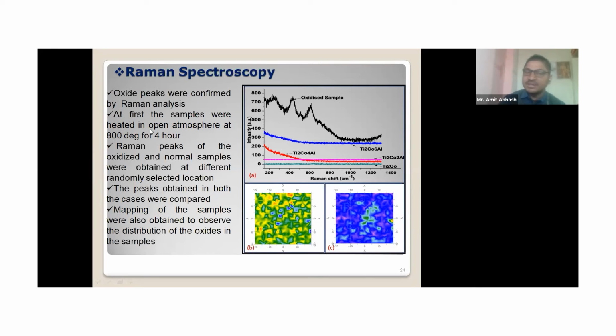At first the samples were heated in an open atmosphere, not in vacuum, because we intentionally oxidize the sample to compare with our sample: 800 degrees for 4 hours. Raman peaks of the oxidized sample and normal samples were obtained at different randomly selected locations, and the peaks obtained in both cases were compared. We also did surface mapping, where this yellow part shows the oxide formation, and this is our sample. We can see here that no yellow part is obtained, so now we are sure that no oxide formed in the entire region.